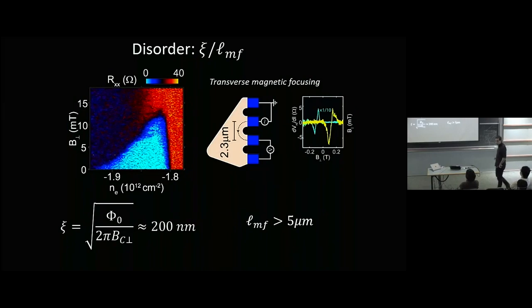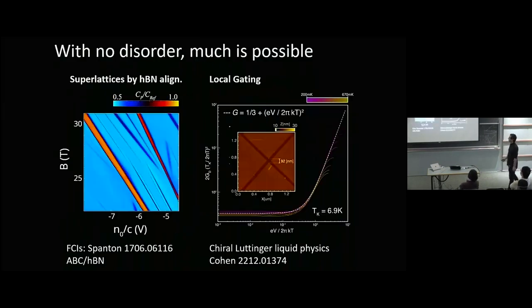What are these superconductors? One simple thing you could try to do is estimate whether they're dirty enough that they should be s-wave. Turns out that's not very useful here because you can measure the coherence length and it's a couple hundred nanometers, which is actually pretty long by the standards of, let's say, twisted bilayer graphene. But the mean free path is many, many microns. You can see that because you actually see ballistic electron focusing over the size of the device, basically between contacts, as you apply some magnetic field. So it's great because the systems are clean. It's not great because it doesn't solve the superconductivity problem.